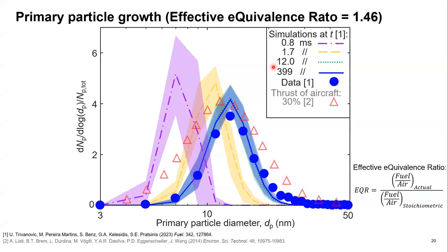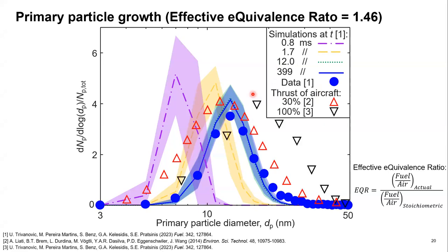We can, of course, also compare to literature on soot from real aircrafts. In the red triangles, we have at 30% thrust, and the inverse black triangles, 100% thrust. And I've chosen these two particular distributions because they represent the range of sizes that we observe in aircrafts, with 30% being the lower end and 100% being the higher end. So most primary particle size distributions from the literature fall somewhere in between these two.